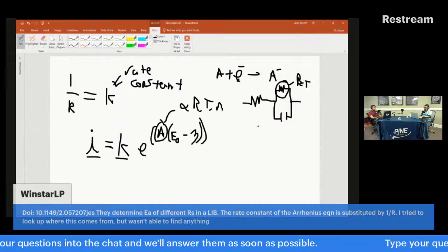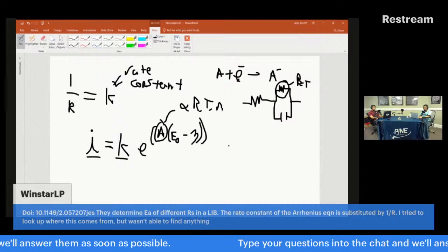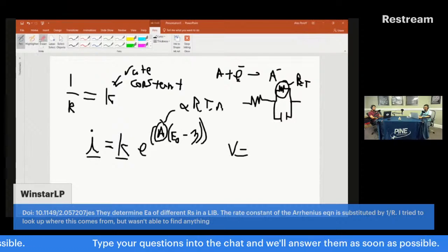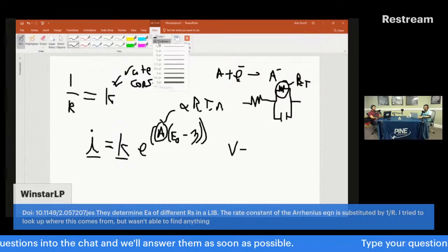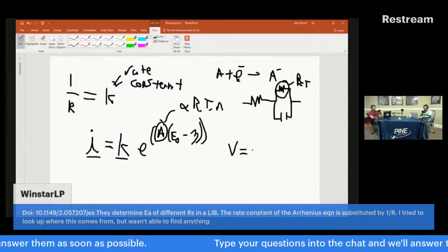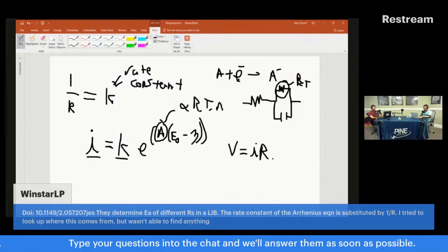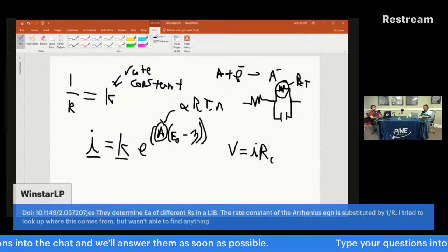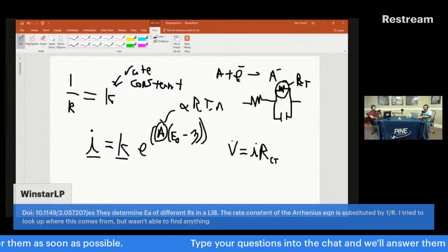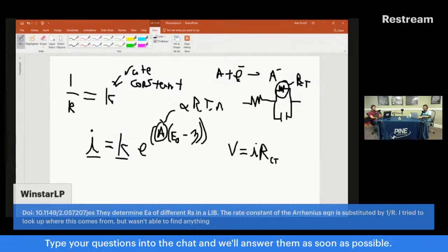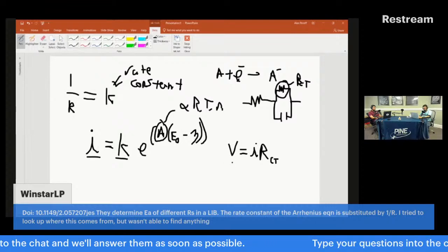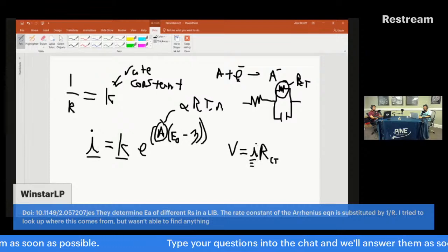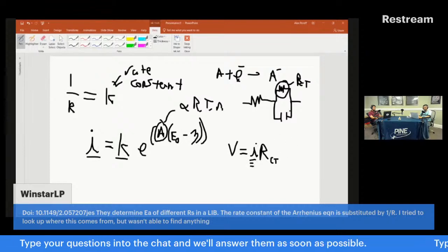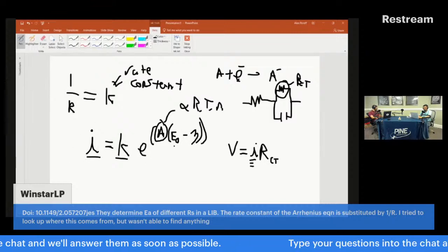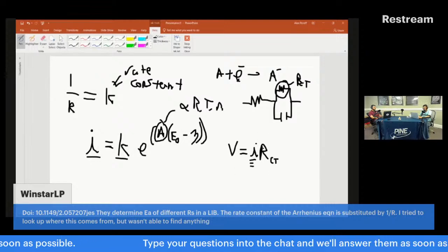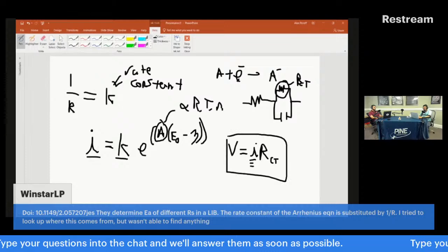So if we think about this in a very simple way, just using Ohm's law, where V equals... oh God, what is with this line? Trying to draw quickly and describe things. If we just look at Ohm's law, V equals IR. If we know that this R is RCT, then we should know that with an applied voltage, which in this case might be a sinusoidal voltage in EIS, at some DC offset, all of the current associated with the resistor associated with charge transfer is a Faradaic process. So all of this current that's useful in a kinetic experiment follows this relationship.